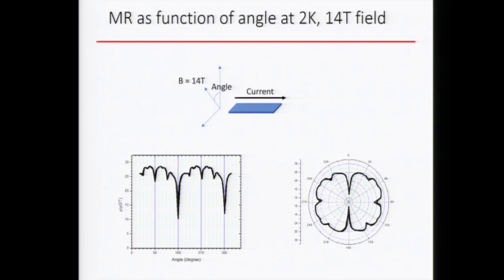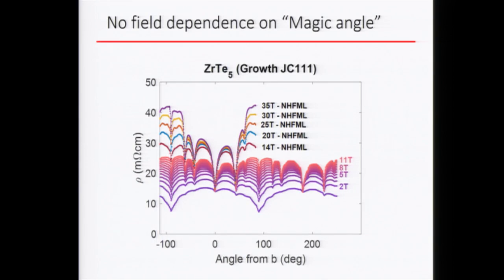But if you go down to low temperature, not very low, 2 Kelvin, and go to high enough field, let's say 14 Tesla, then you see very distinct peaks emerge at these specific angles, right? This is quite surprising because you're already surpassing the quantum limit. There's just no way to get more features when you're rotating the magnetic field. And it couldn't be SDH oscillation because the location of this peak doesn't depend on the field you apply. We go all the way up to 35 Tesla, and the peak remains at the same position.